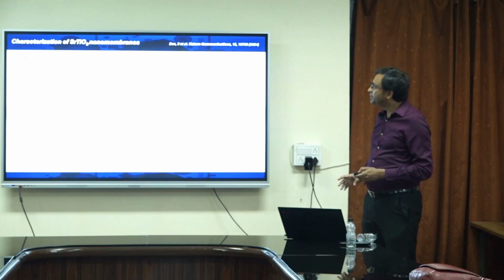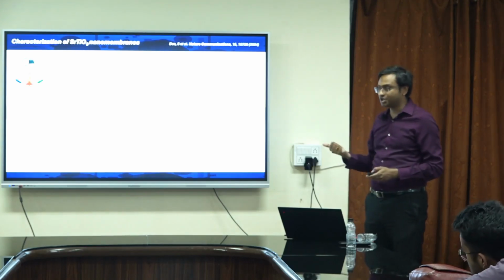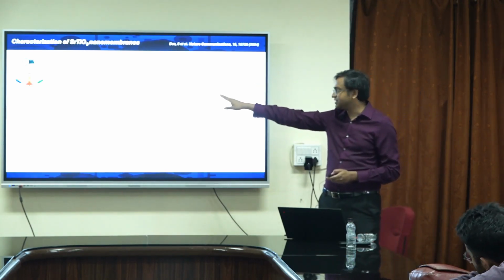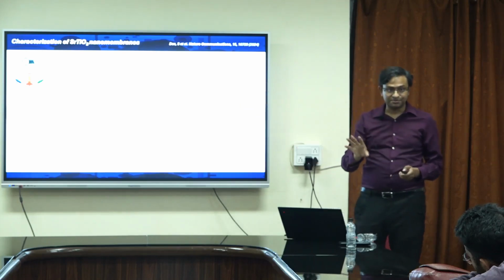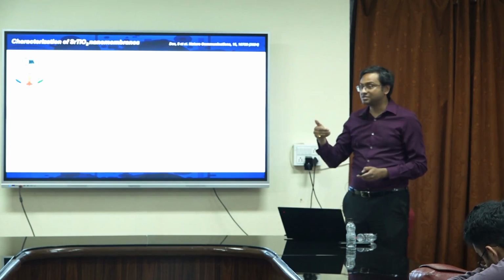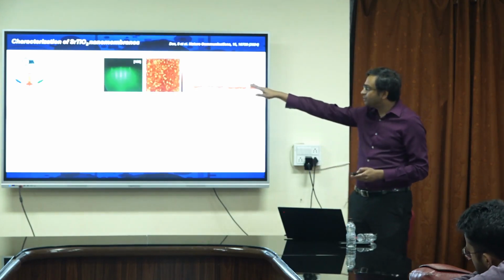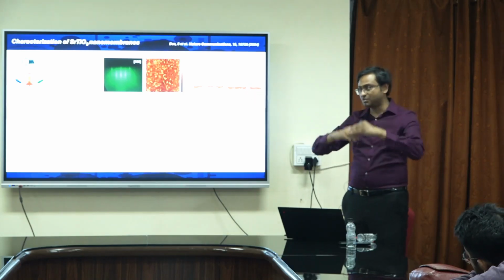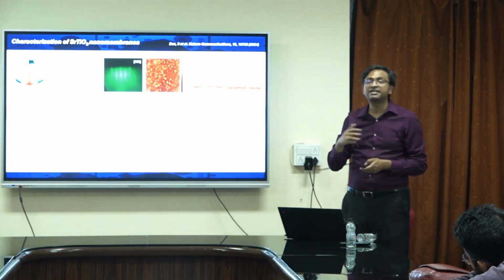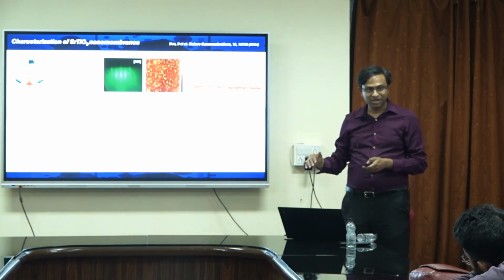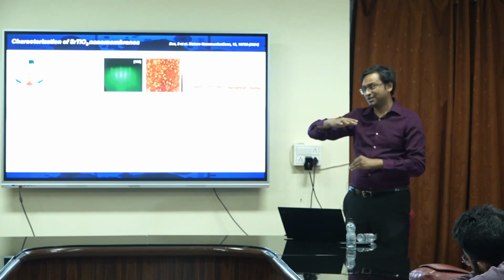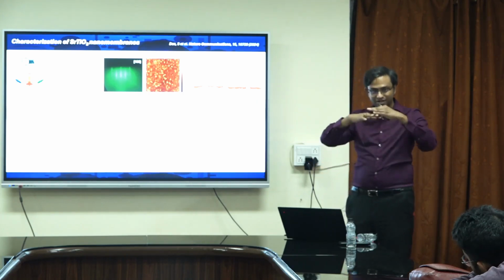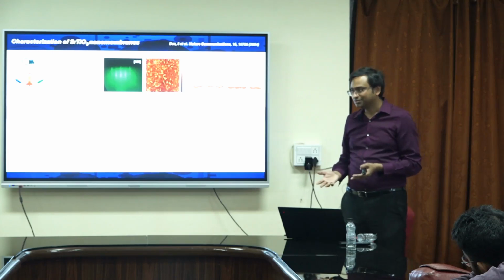and what we are trying to do. So we are actually trying to create these nanomembranes of strontium titanate. As I told you, in earlier days this could only be grown on an epitaxial substrate. This LAO is a lanthanum-based substrate, but now there are some interesting techniques that have been discovered, where you can put a sacrificial layer of strontium oxide, which is also epitaxially matched, and grow these strontium titanate films, and this strontium oxide layer can be dissolved in water. Okay, which means now I can create a freestanding film. Like we've talked about 2D films, nanosheets, we can create nanosheets of strontium titanate. And once you can delaminate it, you can put it on anything, right?